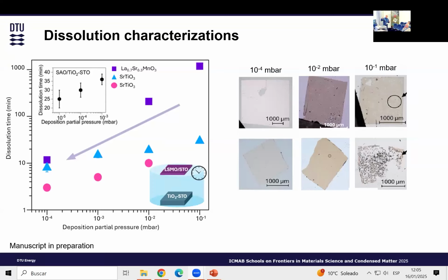and also do the AFM. Now I don't have a lot of time to go into details. What I want you to remember is that we think that the dissolution time depends on the amount of oxygen vacancies at the strontium aluminate part. So if you're able to put enough oxygen vacancies, then the dissolution time will decrease. Now, faster dissolution time is also not good. So you have to find the balance between the speed and the quality of the membranes.